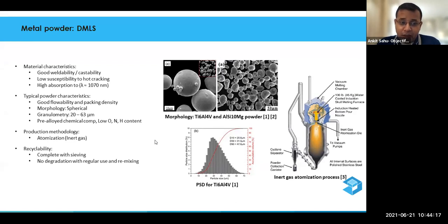The typical powder characteristics should be good flowability and really high packing density. The morphology, the shape of the powder, should be spherical, and the particle size distribution should be between 20 to 63 micron, depending on the alloy itself and its processability. You can have a range from 15 to 45 or 20 to 63. It is a subjective issue, we can discuss it later.